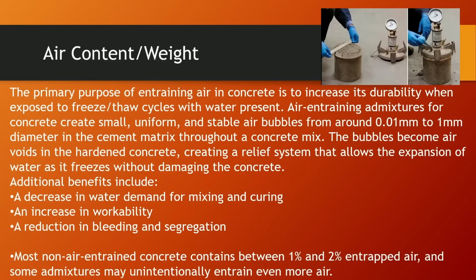Okay, so the primary purpose of entraining air in concrete is to increase its durability when it is exposed to freeze and thaw cycles with water present. So air entraining admixtures for concrete create small, uniform, stable air bubbles from around 0.01 millimeters to 1 millimeter in diameter in the cement matrix throughout the concrete mix.